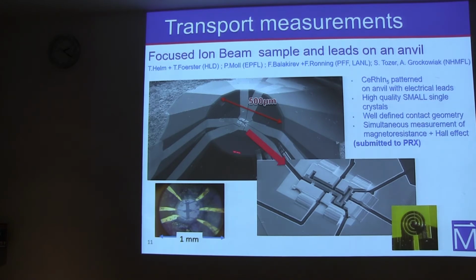Here you see the picture of the culets of our diamond anvil, again 500 microns in diameter. What our colleague at the pulsed field lab in Dresden does is he takes a sample, this clear part that you see in the center of the culet, and blown up, this is the sample, the whole white region. With focused ion beam, he designs a device, as he calls it, and he also creates well-defined contacts on the sample.